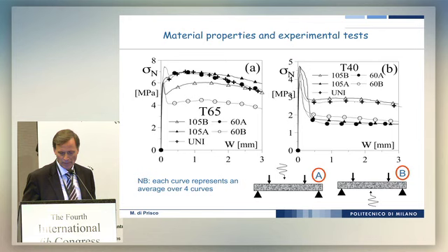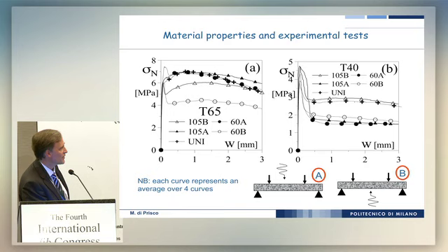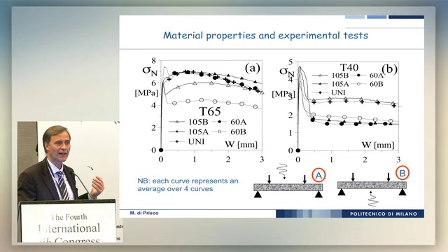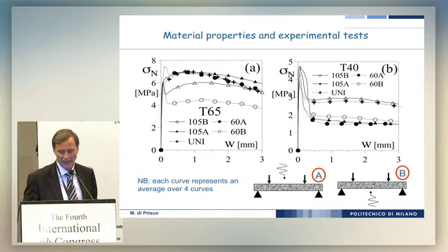You see that in some cases, you have that the four-point bending test, which is case A, gives us the best nominal strength versus crack opening, and the other cases are close if you have, for instance, this casting direction and you test in this way, but if you reverse the specimen, you can have something different. So for instance, in the case B, that means the case with the empty symbol, you have the worst situation. That means that it's not true that if you reduce the thickness, always the orientation factor increases, and so you have something which is better than the conventional three-point bending test. So it depends on the concrete and the sedimentation and a lot of other parameters.